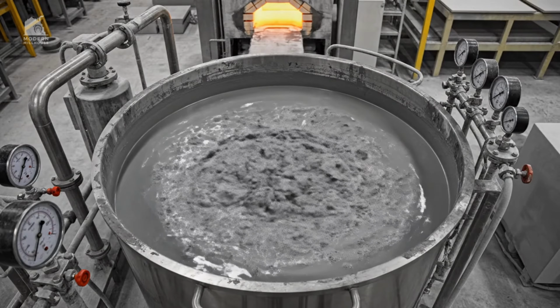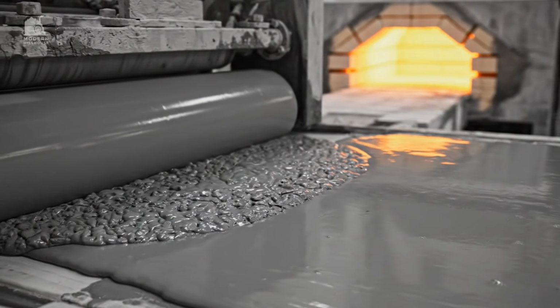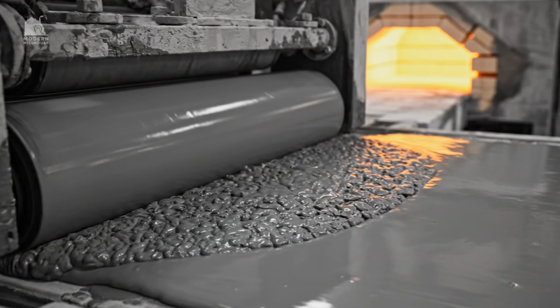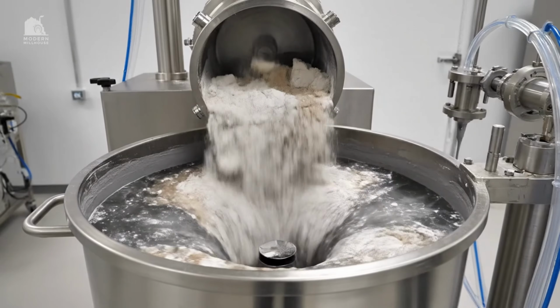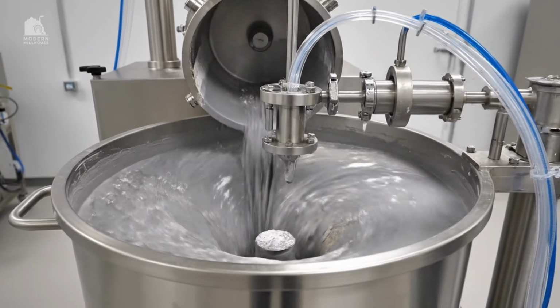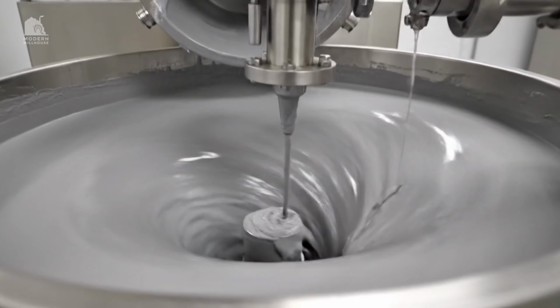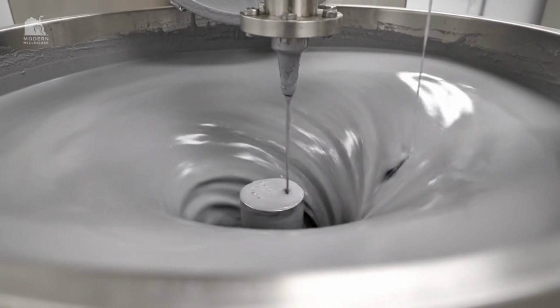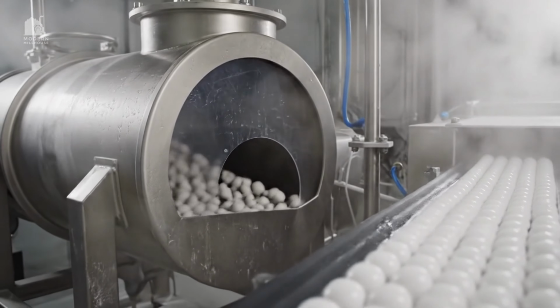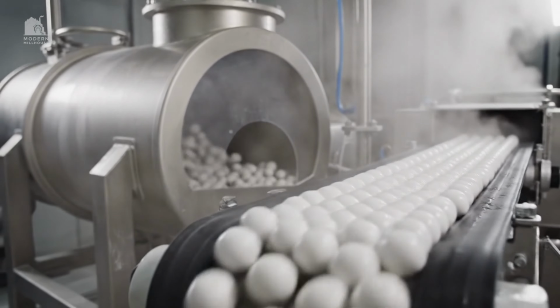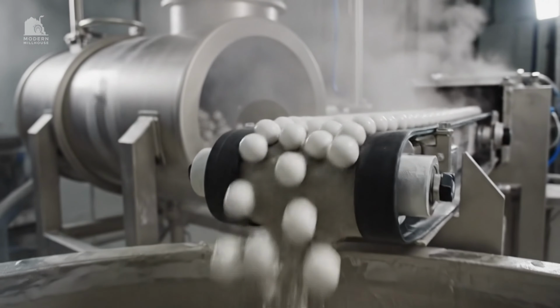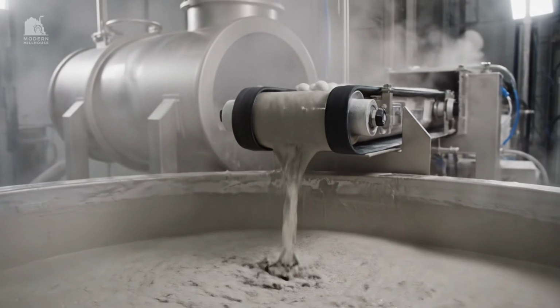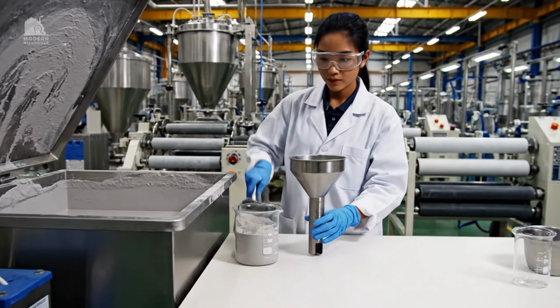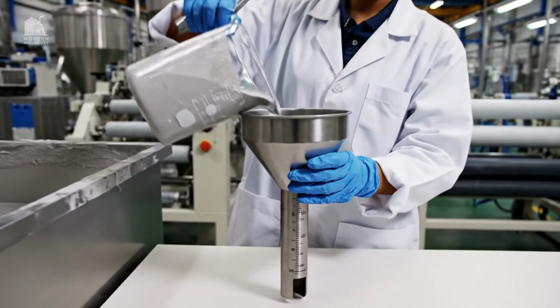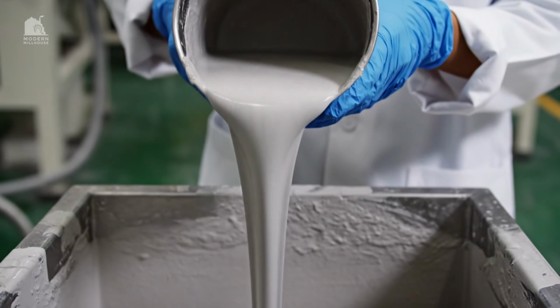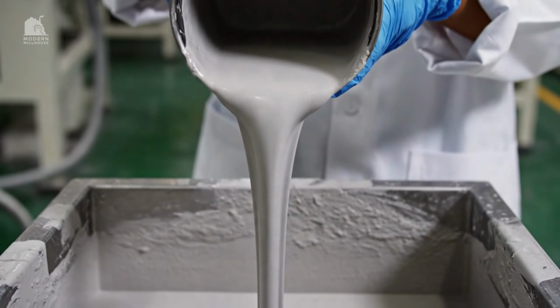Inside the mill, time and speed are adjusted so the slurry reaches a target fineness without over-grinding. Overgrinding can make the body shrink more, and it can increase the risk of warpage in large tiles. Plants also control solids loading because thicker slurry saves energy but requires stable dispersal. If dosage is too high, the slurry can become unstable and settle, creating inconsistent feed to the spray dryer.